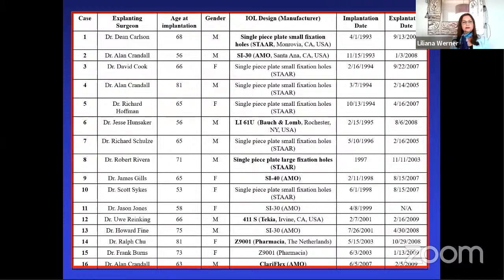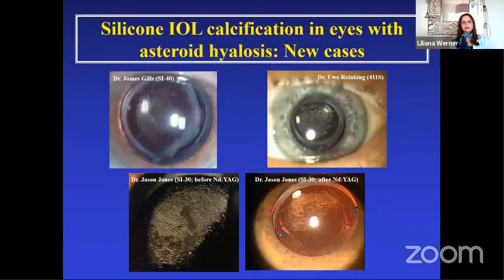This study is an important one because it described 16 cases of calcification of silicone lenses. They were of different models and made of different silicone materials, including older materials and more modern materials with higher refractive indexes. The pattern of opacification was always the same. Calcification only on the posterior optic surface that could be partially removed with a YAG laser, but with reaccumulation of the deposits after the procedure.